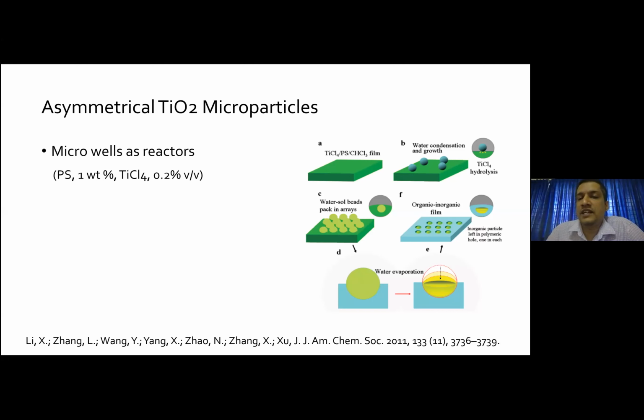They took titanium chloride, polystyrene and chloroform in an optimized ratio. They allowed water droplets to condense onto the surface. Since titanium chloride is highly reactive to water, it reacts and forms titanium oxide, and since this titanium oxide is confined to these water droplets as a nano or micro container, you generate these kinds of particles onto the surface. Due to evaporation, initially the titanium dioxide will be spherical, and slowly it flattens out.